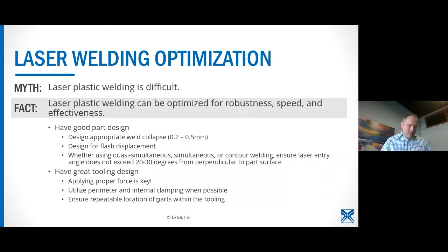That's correct. And then for the gap, there should be a slight gap at the end of melt. You do not want a hard stop. Yeah, so great comment, Ben. We will often see, and if we're recommending, a gap of 0.2, 0.3 millimeters, depending on the part size. It really varies, but yeah, good observation.